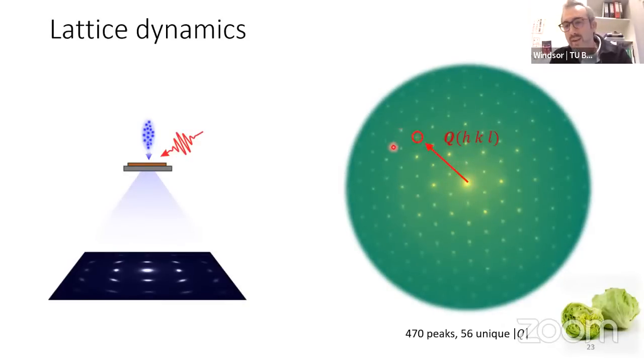And what you see here is many, many diffraction spots. Each one of them is characterized by a unique, what we call Q. It's a scattering vector, which we can describe using Miller indices, and reflects a distance in reciprocal space. So the distances in this picture are in units of inverse distance, or momentum, if you will. And what we want to understand is what happens to these peaks. How do they change? So I'm going to initially show a quick result followed by a more detailed result, and you will understand in a minute why.